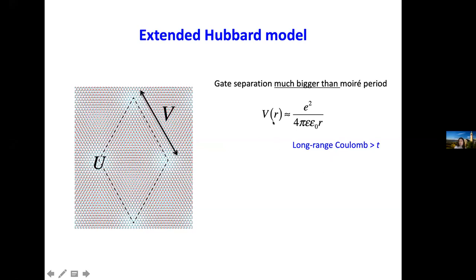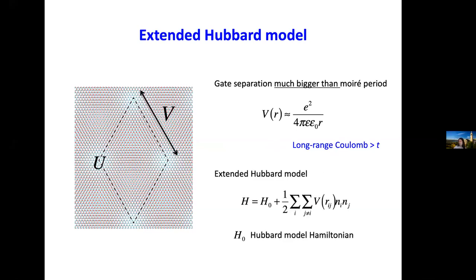The intersite Coulomb interaction is not very well screened. So the simple Hubbard model with only on-site repulsive interactions is not adequate to describe the system. We have to include the long-range Coulomb interactions. But if we only consider the fractional filling, double occupancy is unlikely. So in that case, you can make U go to infinity and drop this term.